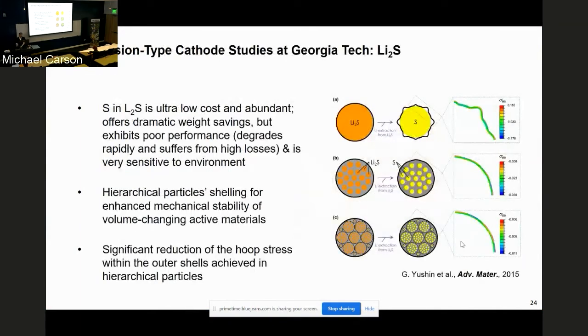Now, once you develop and scale up the anode product, then the next step is to develop conversion type cathode materials. And one of those promising candidates is sulfur-based lithium sulfide. And sulfur, as you know, is low cost and abundant, and enables you to achieve significant weight savings for the batteries, but also exhibits very poor performance. It degrades rapidly. It suffers from very high losses. It's very sensitive to environment. You can't process it in conventional factories.